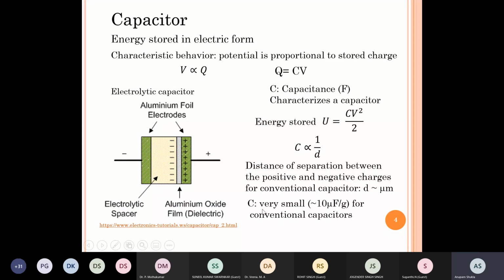And when that happens, the capacitance usually obtained is about 10 microfarads per gram for a conventional capacitor. Now, for example, the capacitor that is used in our ceiling fan, I believe that most of us have encountered that during operation after some years, the speed of the ceiling fan becomes slow, and usually the rectification is that the electrician comes and changes the cylindrical unit, which is essentially this dielectric capacitor. And by the way, the amount of capacitance in that device is also in the range of 1 to 10 microfarads. So that's how low the capacitance is, but then this capacitance is still useful to run many electric circuits, electric appliances.